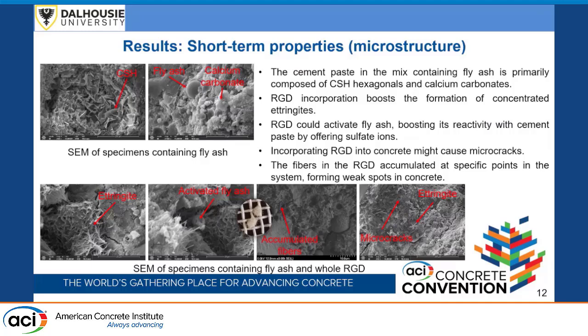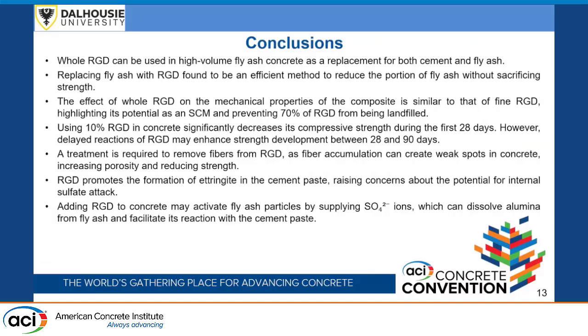And for the fiber accumulation, you can see the fiber accumulation here. So these are the fibers that accumulated on the sieve, and this is the fiber accumulation that we saw in the SEM image. So this fiber accumulation could form weak spots in the concrete. So by treatment or refining the recycled gypsum drywall to remove the fibers, we may improve its performance. And so based on that, we go to the conclusion.